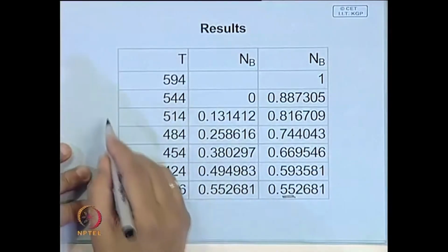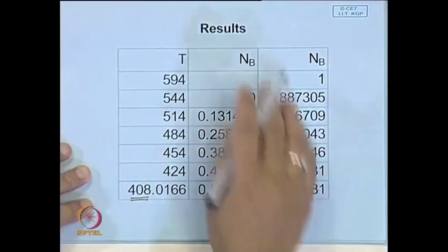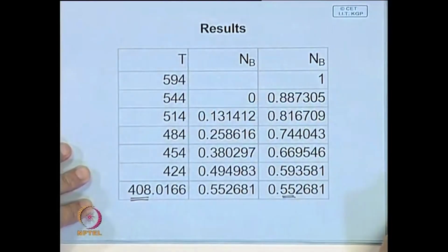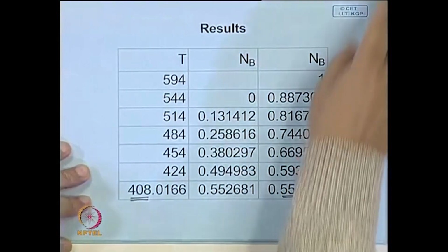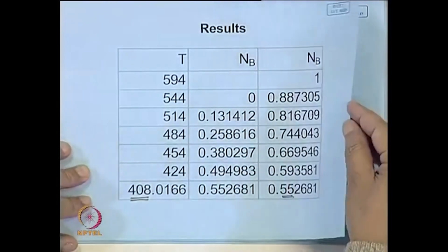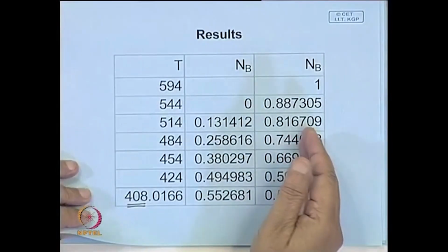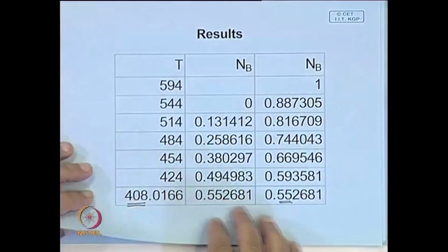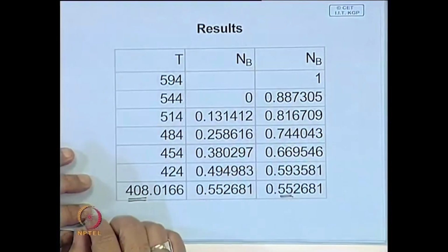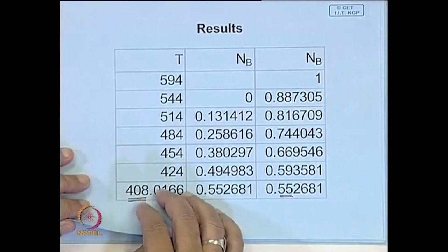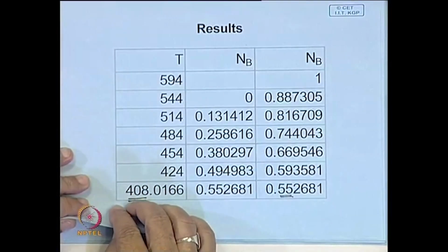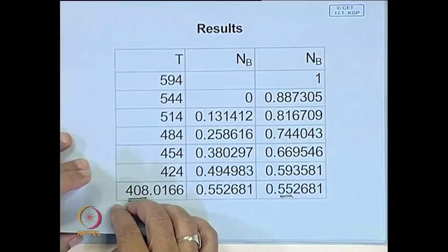So, that means you have to question these assumptions, but this is a procedure which is applied, and in one way you can say that thermodynamic properties are also evaluated from the phase diagram. You determine it experimentally and then try to conclude whether that liquid solution is ideal or not. If it is not ideal, from this it is possible to calculate how much its deviation from ideality is.